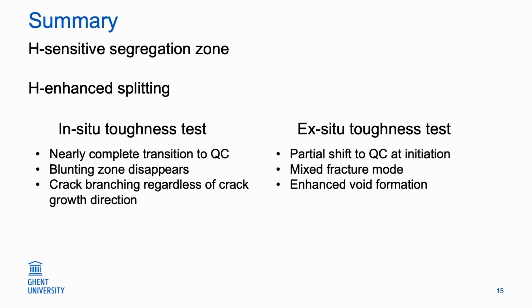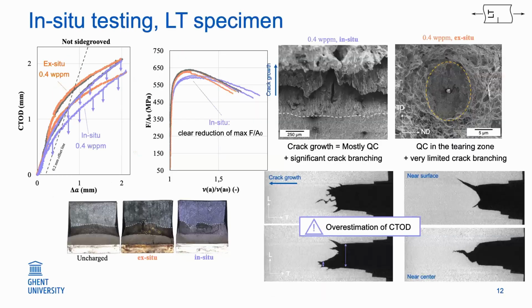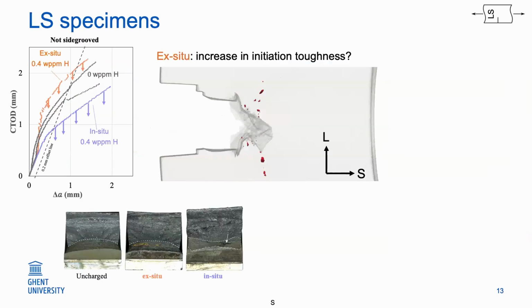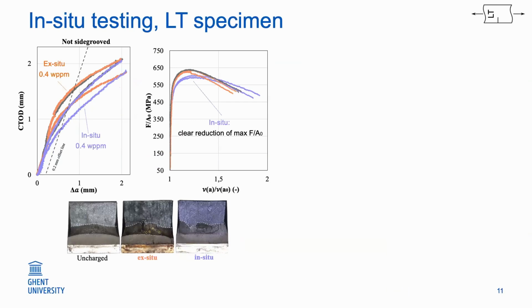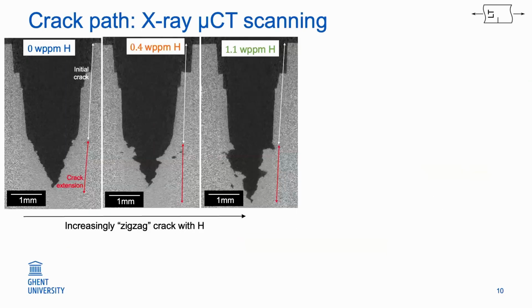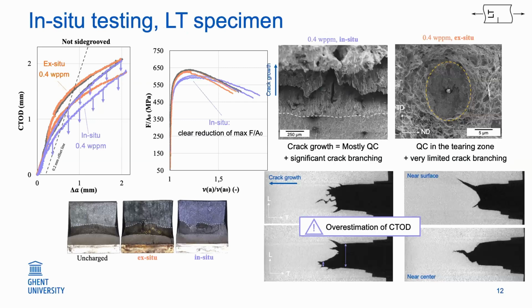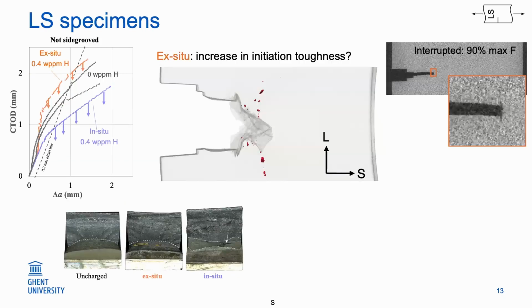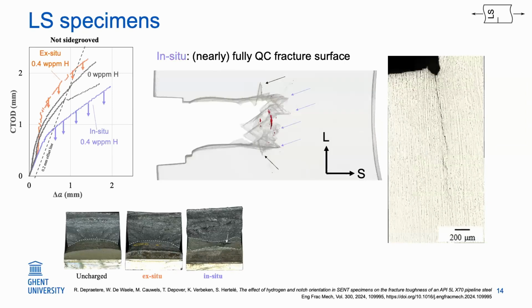Also, the fact that we see maybe less void formation in our in situ tests is because these crack branches are all connecting the voids, because the red areas are of course open volume, so completely surrounded by steel. If they connect to the air somewhere, the CT scan will not really pick it up in this kind of picture. So it can be that we still have this increased void formation.